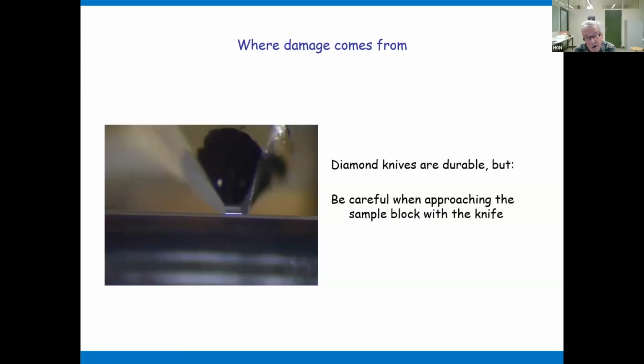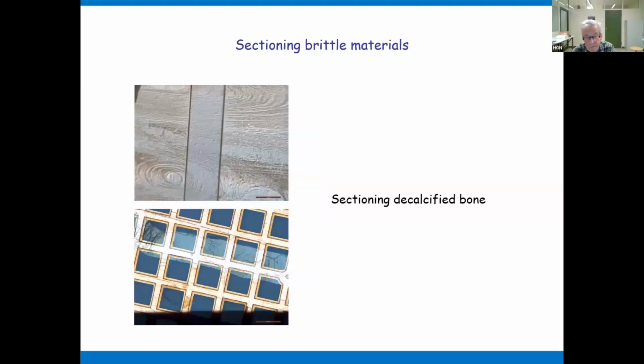The approach of the sample block with the knife may be critical. I see 99% of ultramicrotomists moving the sample block up and down to see the light gap. This is all fine as long as the light gap is there. But if you touch the sample block with the knife and you move the sample block up, you have damage, then you have a lateral force.